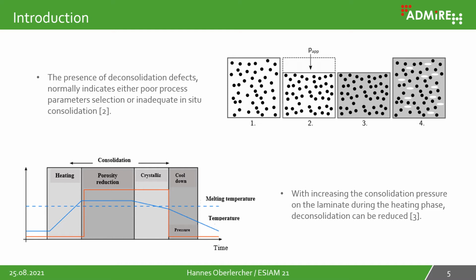It is an indicator of poor process parameter selection or inadequate in situ consolidation. How can we reduce this deconsolidation? With increasing the consolidation pressure on the laminate during the heating phase over time. You can see it here in this graph, the whole consolidation process. It consists of 4 phases: the heating phase, the porosity reduction, the crystallization phase, and the cool down phase. In these 4 phases, it is important to have the correct process parameters over time. With this strategy, you can reduce the cavities inside and enhance the material properties.